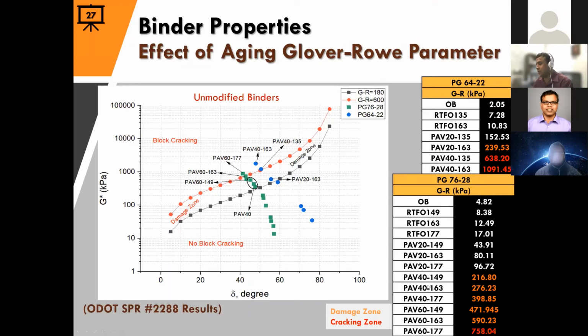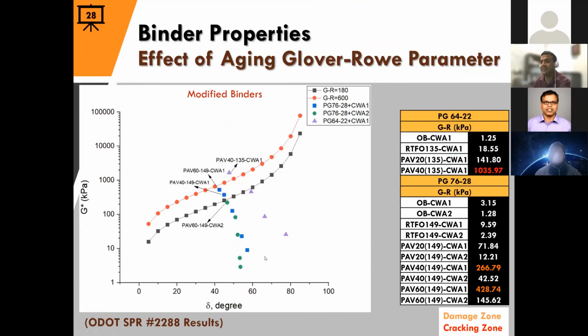Similarly, for this one, you have 149, which is 76-28. Of course, for such a stiff binder, you really don't do 135. That's not going to help you at all. So we do 149, 163, 177. And after that, we do PAV 20, 40, and 60. We're doing 3 cycles of PAV. And this is the data, but I'm going to skip over it for now.